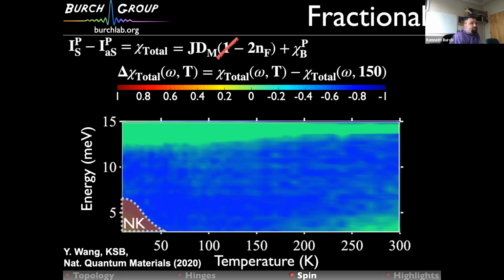So do you actually see a gap? I mean, if you go below TN? So we don't. There's another group that has gone below the Néel temperature, and they indeed do see a gap in magnons. No, I mean at the gamma point. At gamma. Yeah. It's not really a 1 magnon, it's a 2 magnon excitation that they see. What's the size of the gap? That's a good question. I think it's on the order of 1 meV, but it's been a little while since I looked at their paper. Yeah, maybe 2 meV, something like that. It's sort of just on the border of where I can measure, to be honest.